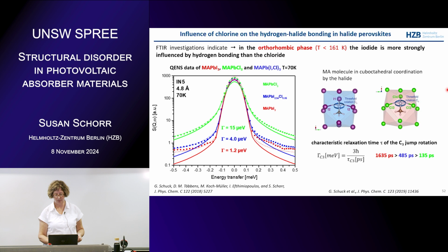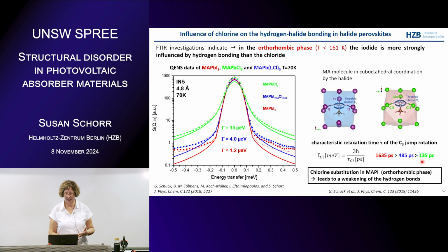This is, for instance, for the C3 jumps. These are the jumps along the carbon-nitrogen axis. So in principle for MAPI, it's 1,635 picoseconds before it jumps to the next. And this decreases when you go to the pure chloride, and this is just with a little bit of chloride. And you see that this decreases, and this is a hint that when you substitute chloride for iodine, this weakens the hydrogen bonds a lot. So the bonds between the hydrogen in your molecule and the halide.